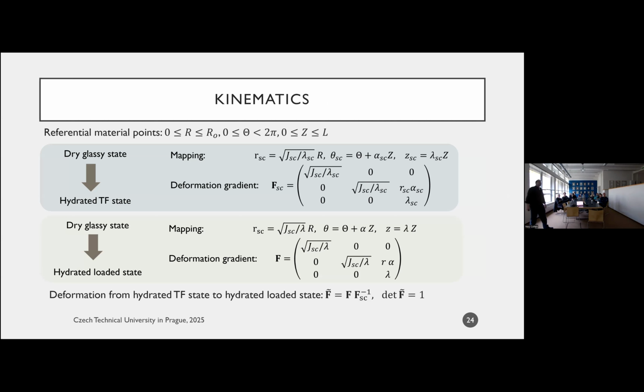And so this is the mapping, right? You can quantify, so this is fairly straightforward. This is the mapping, the deformation gradient from the glassy state to the traction-free state. This is the mapping from the glassy state to the hydrated loaded state. And once I know the deformation gradients, I can compute the overall deformation gradient from a traction-free state to a loaded state, right? So I can do all of these.